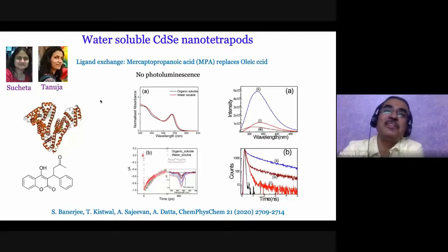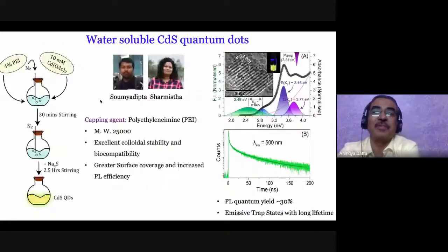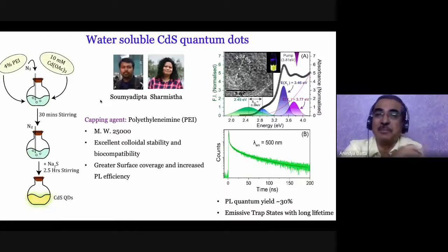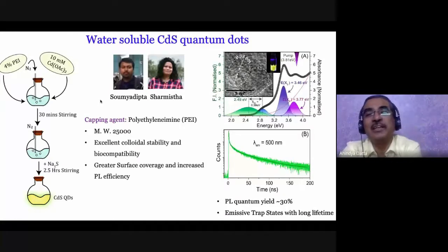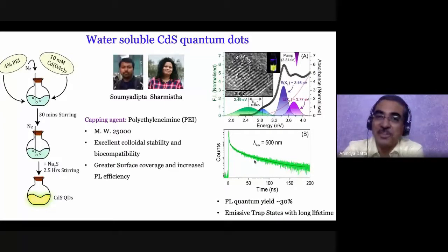So in our quest for water soluble nanocrystals that were fluorescent, Soumyadipta, a postdoc who is now doing a second postdoc in Spain, and Sharmistha once again, figured out a way. Most of the synthesis is reported in literature, except for this doped tetrapod. So they figured out a way of making cadmium sulfide quantum dots that are prepared in water. These quantum dots are actually very strongly photoluminescent. You can see this photograph here, how brightly they are glowing, and the lifetime that you get is in tens of nanoseconds. Remember, longer lifetime means stronger fluorescence also.